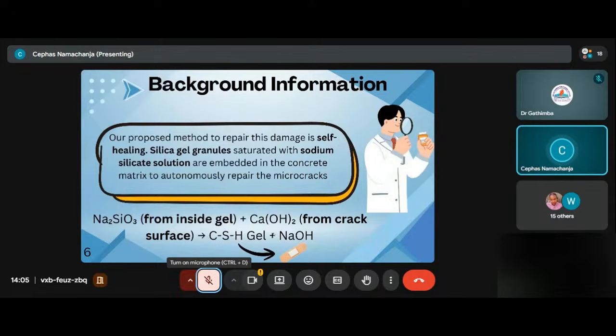The microcracks act as direct pathways for chloride and other deteriorating substances that penetrate the concrete cover, reach the steel reinforcement, and corrode it. So existing strategies such as improving the mix or using surface protections, yes, they are protective measures, but they don't autonomously repair the damage. Our proposed method is self-healing using sodium silicate.